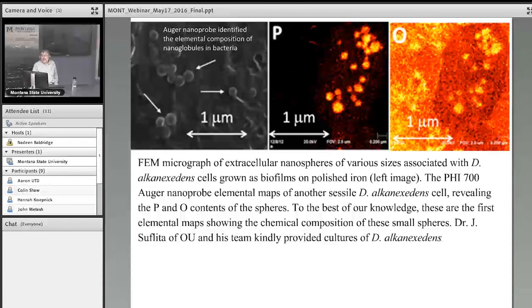We tried very hard to get elemental information on them. So here it is with Auger. These are not done in our lab. It's done with the system we have, but we send them out. They were doing it free, otherwise $800 an hour. We got them done because we were essentially getting the system from them. So you can see they were phosphates. What you do with that, I'll leave to the microbiologists, but these organisms are storing something to survive the bad days ahead. So, almost there.